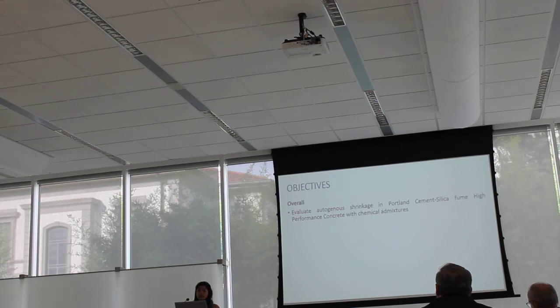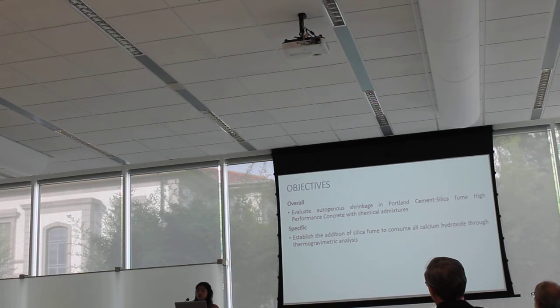The main objective is to evaluate the autogenous shrinkage in Portland cement silica fume high-performance concrete with chemical admixtures. The specific objective is to establish the addition of silica fume needed to consume all calcium hydroxide, through thermogravimetric analysis. So we are not going to use different additions of silica fume, just one, but that one has to consume all calcium hydroxide, at least theoretically.